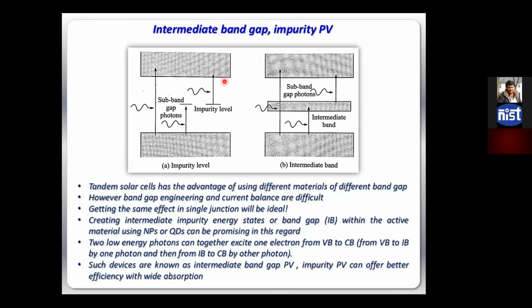So this kind of technology is also coming up, but the problem with these intermediate band gap or impurity band gap approaches is that they do not only help in generation, they help in recombination also. So the more such trap states and impurity levels you have, the easier recombination becomes, and transport becomes a little bit tricky, because when your charged particles are going through the conduction band, they also feel like jumping to the impurity level and getting trapped, right?